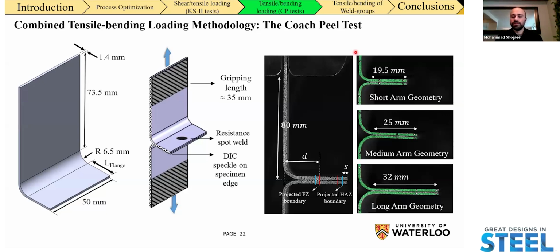I'm going to refer to the Coach Peel test with three geometries: the short arm geometry, where we have a horizontal arm of 19.5 millimeters; a medium arm length geometry with an initial arm of 25 millimeters; and a long arm geometry with an initial arm of 32 millimeters.